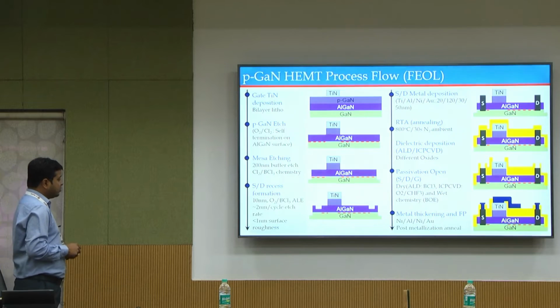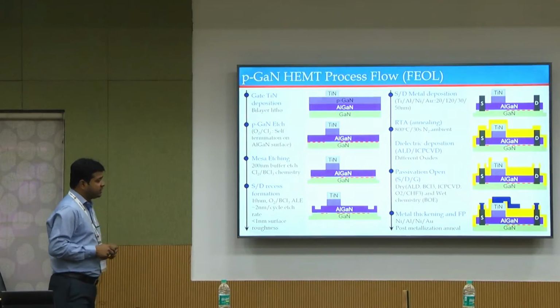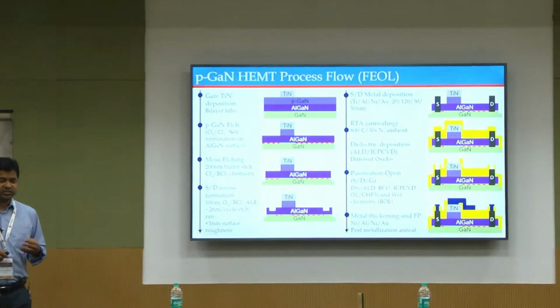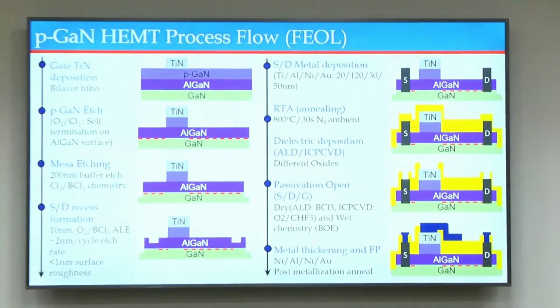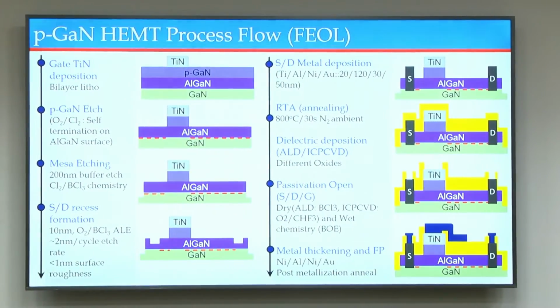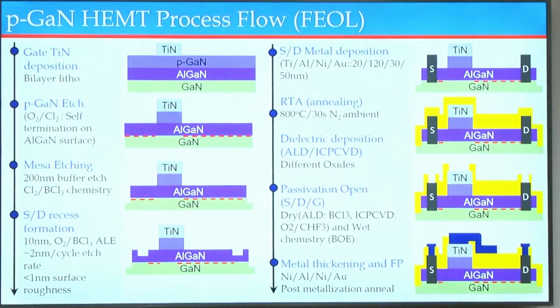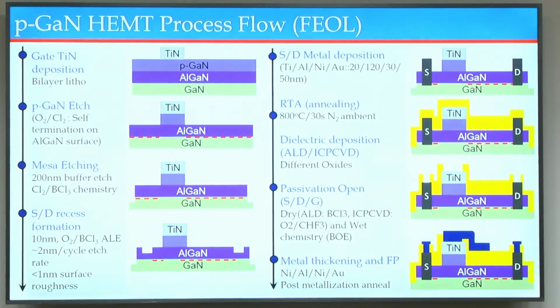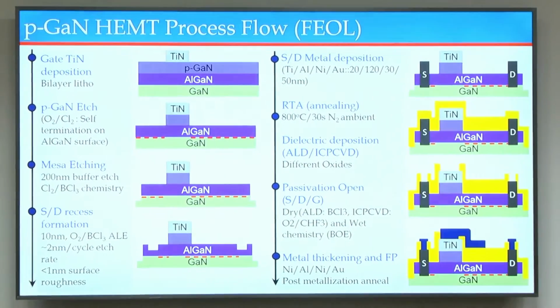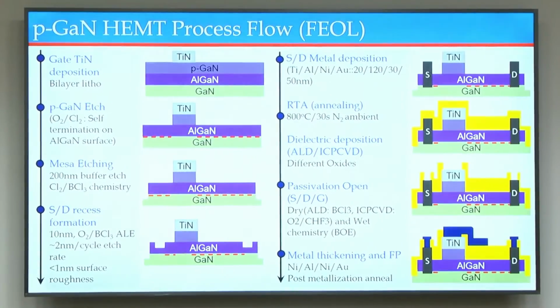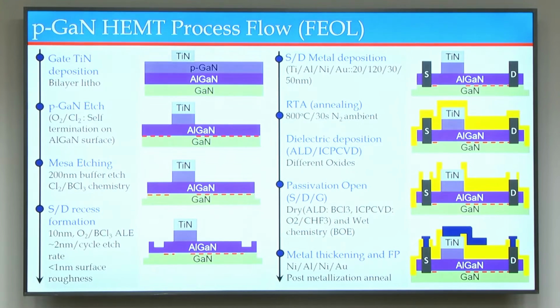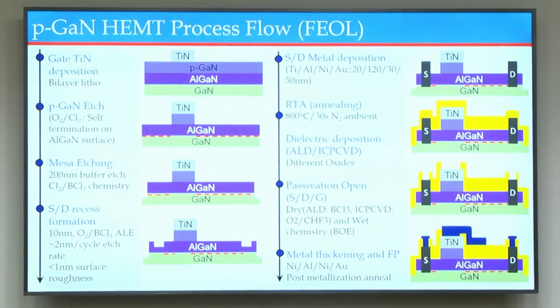Now before getting into the process complexity of pGaN gate based transistor technology, let's briefly look into the typical process flow. So you start with the wafer that you get, which has the pGaN grown on top of AlGaN everywhere. So it's basically a stack where you have GaN, AlGaN and pGaN present everywhere, and if you have to make a transistor, you have to keep the pGaN only in the gate region, which means you have to do a selective etch of the pGaN layer there.